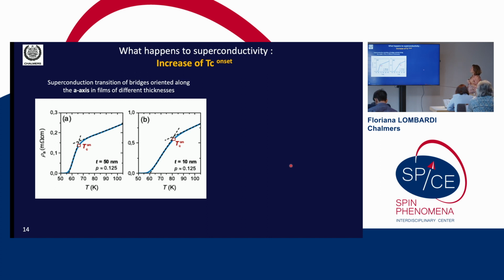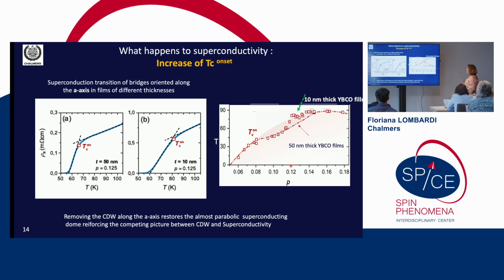Okay, this is the normal state properties. What happens to superconductivity? Then this is 50 nanometer films. These are 10 nanometer films. And you see that the TC onset is increased almost 20 Kelvin, going from 50 to 10 nanometers. And you can make it as a function of the doping, and what you get, you are recovering the parabolic dome here in 10 nanometer films. And this is up to 0.12, where then charge density wave becomes weak, and it doesn't compete anymore with superconductivity. So even though you have removed it in one direction, you will not get any increase, because this depression here is not anymore due to charge density wave.